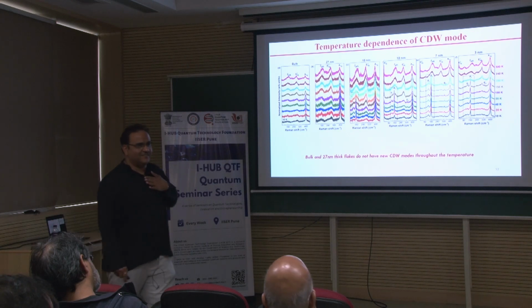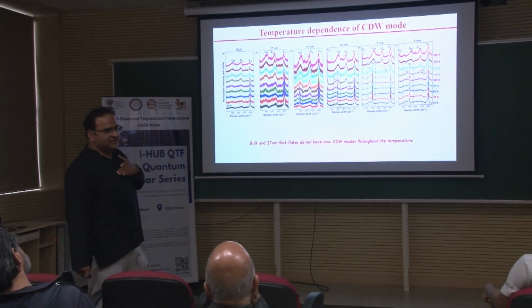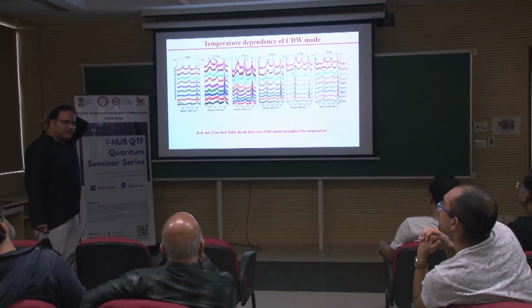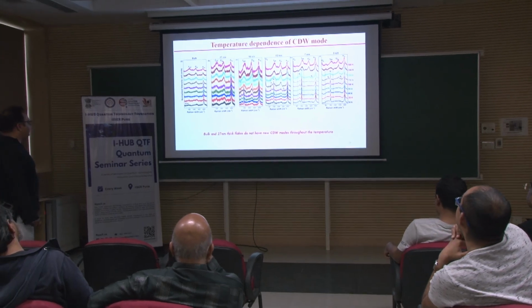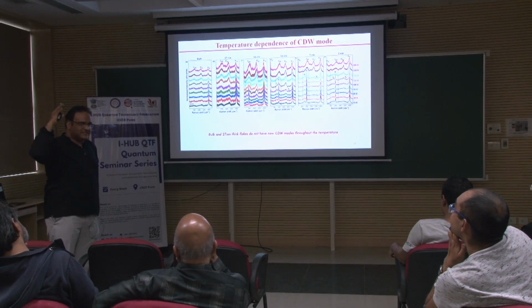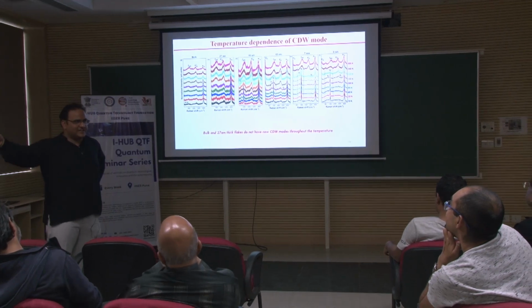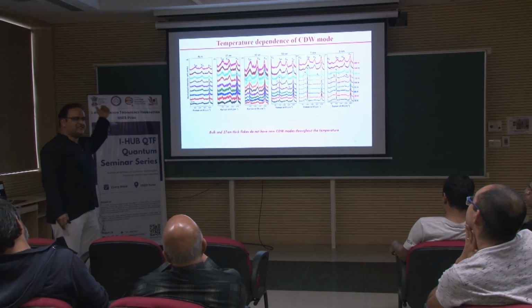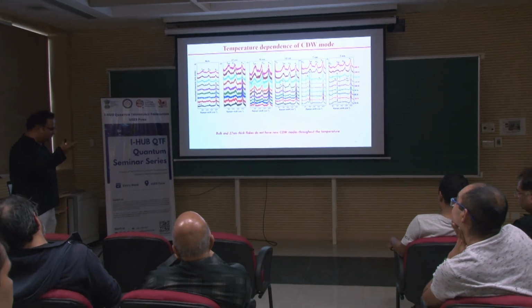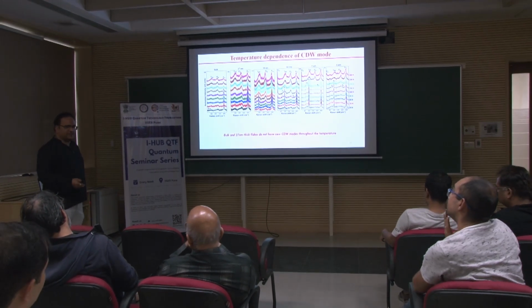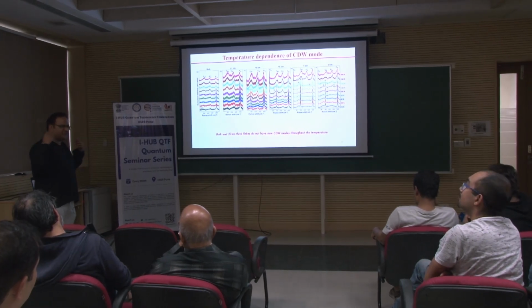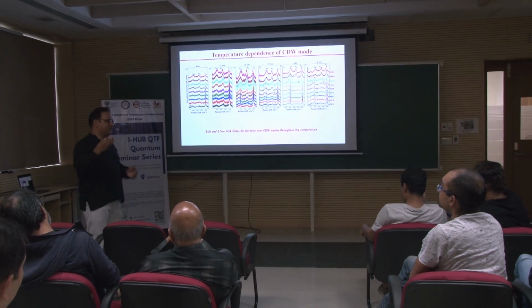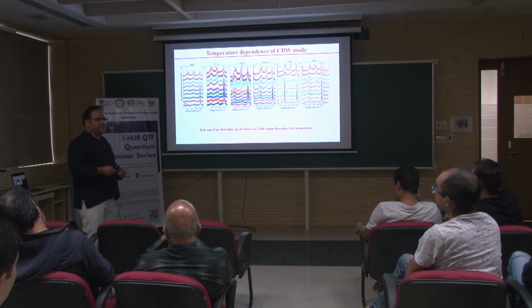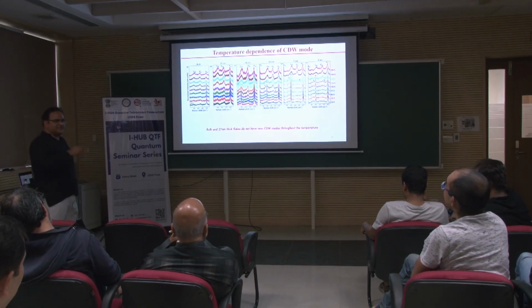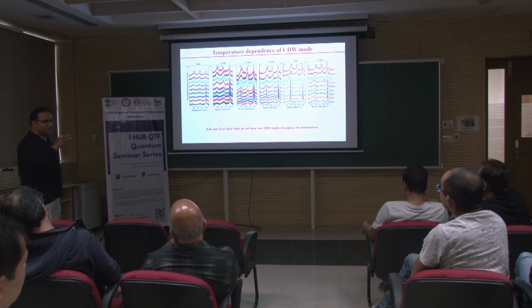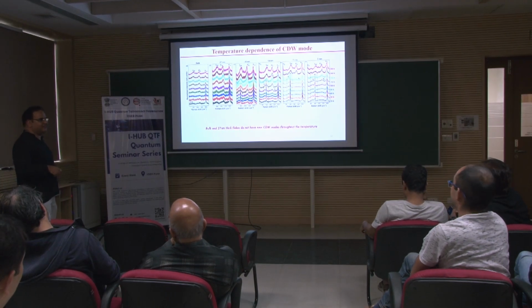Yes. I was curious why the signal to noise ratio goes bad when you go towards thicker plates. Do we understand this? So, when you talk about thicker crystalline samples, you have more scattering processes coming up there. The cross section is less than for the monolayer. For example, in graphene, the cross section is extremely high, so you get extremely beautiful data for the G mode and D mode. But if you take graphite, the noise ratio is larger because the cross section in the monolayer is high for graphene.